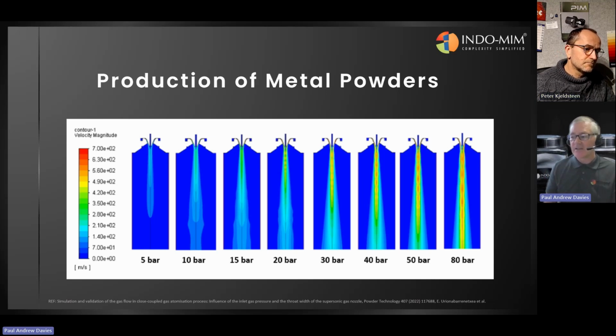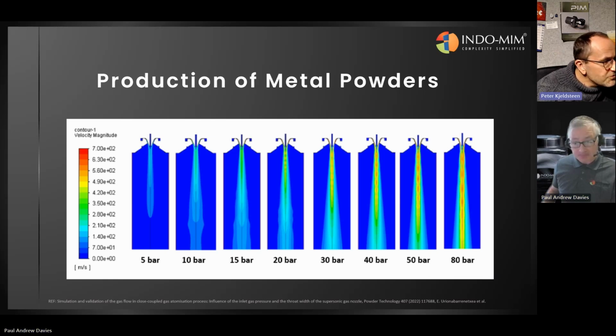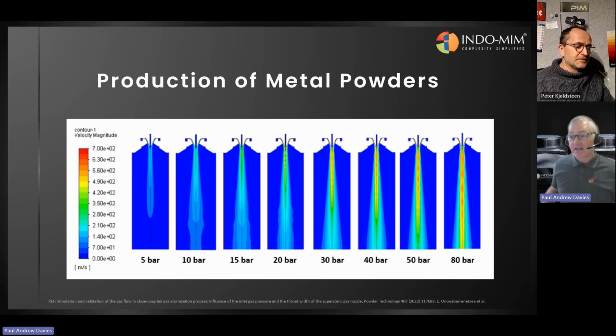But certainly it can yield very good results and trends towards different size distributions, narrow distributions, or finer distributions, for instance. And when it goes red, you go to 700 meters per second. Exactly. So that's Mach 2. Exactly. So it's going very fast. So the pressure has an influence on its speed, ultimately governed by the classic formula PV = nRT. So pressure, volume, and temperature have this basic relationship.